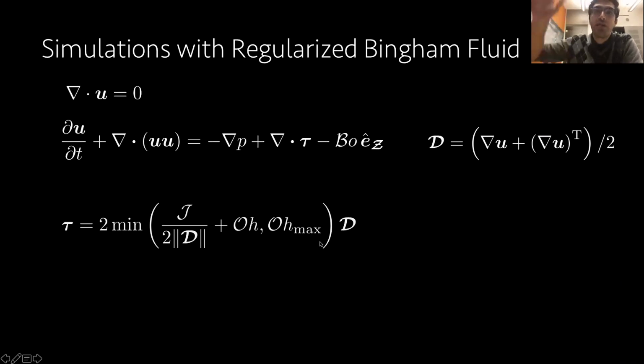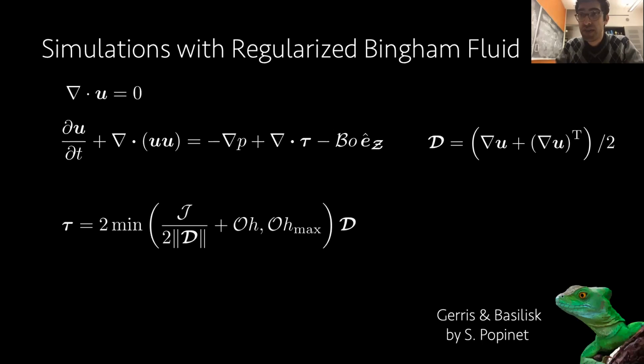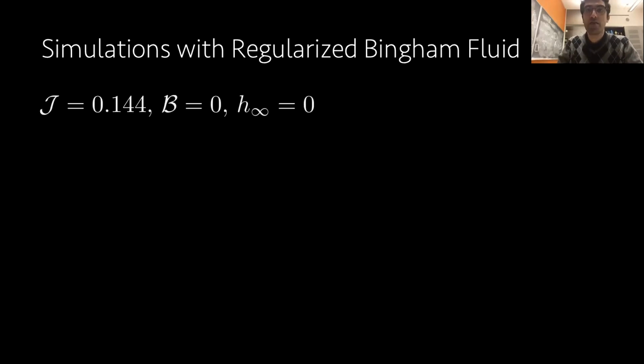So there's an Ohnesorge number, if you will. When the stress goes below the yield stress, my fluid flows with this Ohnesorge max, or large viscosity values. We made sure that our results are quite independent of this regularization parameter, of course. Okay, we use Gerris and Basilisk as our solvers. These two magnificent numerical platforms are developed by Stéphane Popinet, who is at the Institut d'Alembert in Paris. And here are some results for these values.